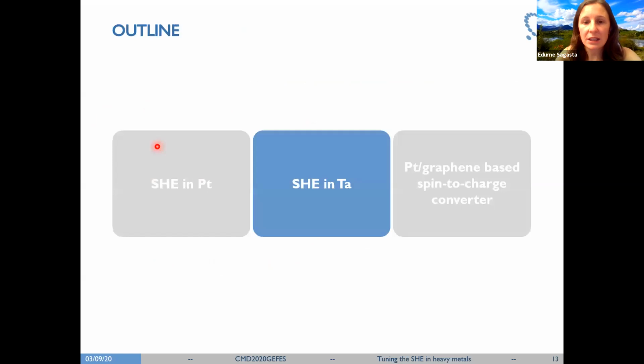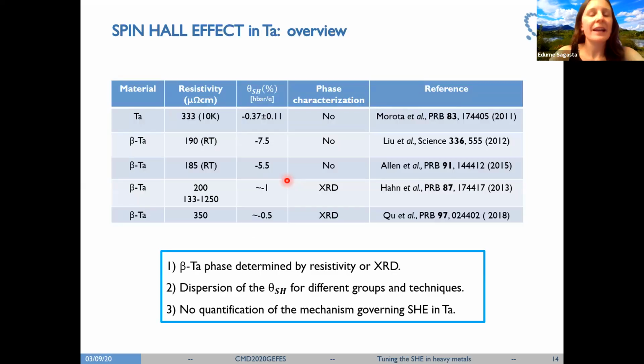So now I will jump to the second part of the talk, where we will see the spin Hall effect in tantalum. Again, if we go to the literature, we can see that there are many different results. First of all, we need to clarify that in the case of tantalum, we can generally find two phases. We have the alpha phase that is metallic, and beta tantalum, which is characterized by a higher resistivity and a negative temperature coefficient. In some of the works, just with the resistivity, they determine which is their phase.